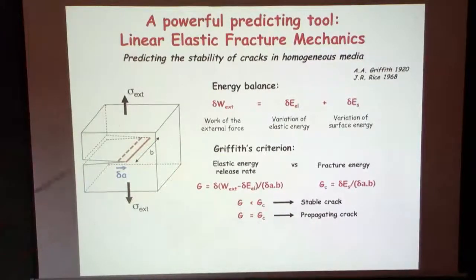So this is the concept of Griffith's criterion. Fracture mechanics is telling you if a crack is stable or not, more or less. The one comment I have about this is that when one talks about the surface energy, one is not talking about a sharp mathematical surface. One basically has a region where elasticity works, and it breaks down on small scales. You're saying, I know how to calculate the elastic energy from the large scales, so everything at the small scales that's hard, I'm calling surface. The crack may disrupt a volume that's micrometers on either side from the crack's face, but that's all thrown into the surface.